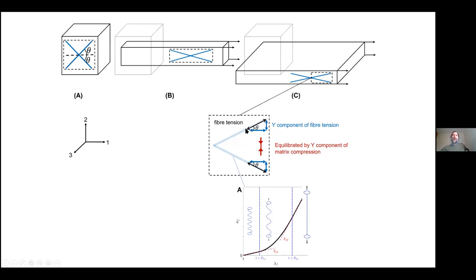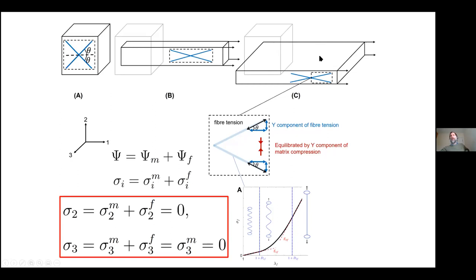So if the fibers reach an angle theta, we have a tension in the fiber that we can decompose into a Y component of tension and an X component of tension here. Now this X component basically is measured as difficulty to stretch the material in the X direction. But what this Y component of tension does is it tends to pull the material inwards. Why is that happening? Well, when I stretch the material in the X direction, the Y direction should be a stress-free direction. In other words, there's no boundary condition on this front surface, so there should be no stress on this surface. So if this is the two direction, the Y direction, that means the matrix and the fiber stress component should be in equilibrium. They should sum to zero. And the same in the three direction.